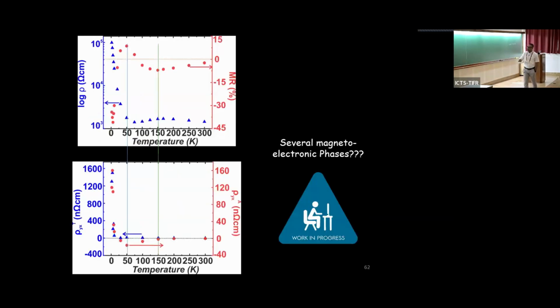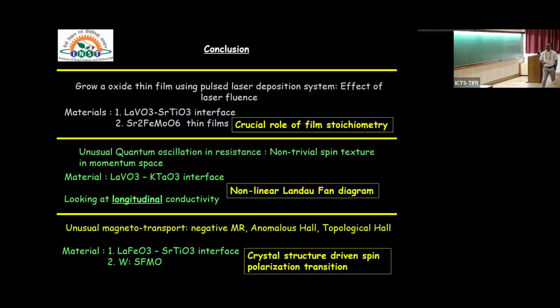So if we summarize all this data, this is temperature versus resistance, this is temperature versus magnetoresistance. You see where the transition in resistance happens, you see the transition in the magnetoresistance. And at this low temperature, there is something like topological Hall effect coming, and at this point, this anomalous part of the magnetoresistance also vanishes. But the important part is that even if at room temperature there is no anomalous Hall effect, you still have a negative magnetoresistance. So we don't understand anything, but we are free to discuss. If you have any question, please ask. So these are the conclusions.